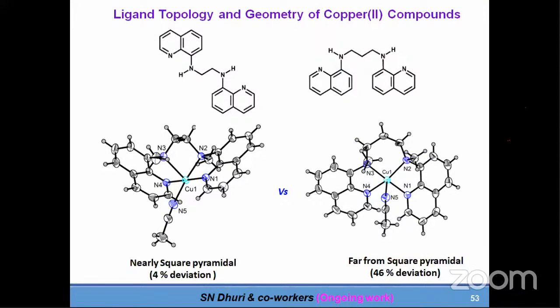In addition, we are also doing some more work. We have prepared many ligands and are trying to do some work. You can see we have prepared one copper compound with this ligand, and this is the crystal structure we have. This is BQEN, as we call it, where NHNH is ethylenediamine. But now, instead of CH2, we have inserted one more methylene group. When we prepare a compound with it, you can see what happens. The structure of the original compound is very close to square pyramidal, but the moment we put one more CH2 group here, the structure deviates almost 46% from square pyramidal.